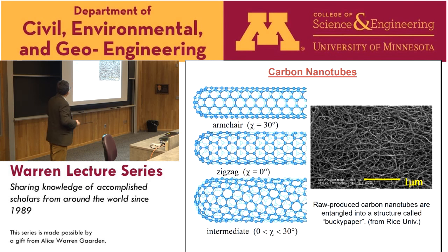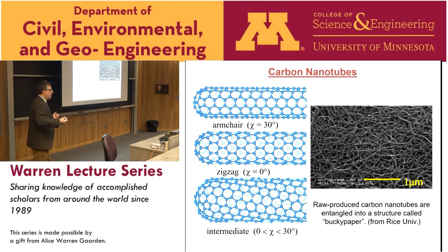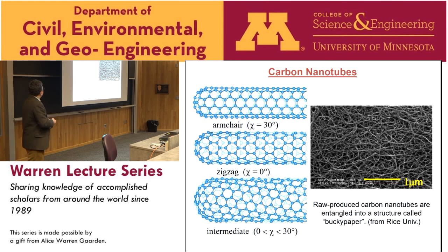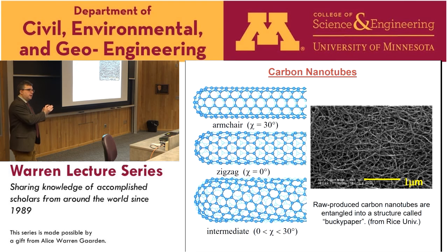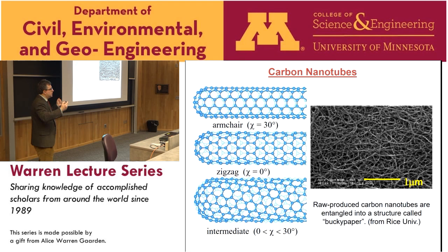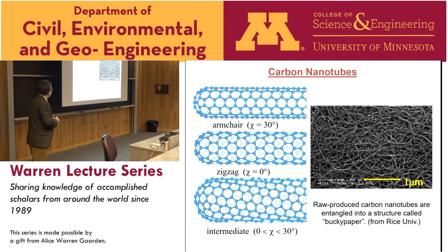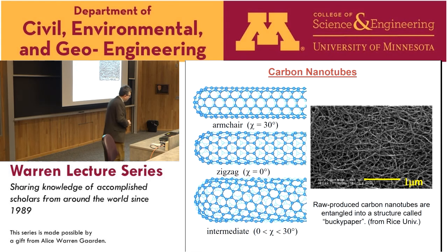More recently there has been more significant progress in producing carbon nanotube materials on a larger industrial scale. The structures produced now by a company called Nanocomp — which was purchased by Huntsman — comprise more often multi-wall carbon nanotubes of somewhat larger diameter. We are moving from one nanometer diameter tubes to ten nanometer diameter with multiple concentric walls. They are adopting a new nomenclature and call it Miralon — the same structure and material, just with different structural features.